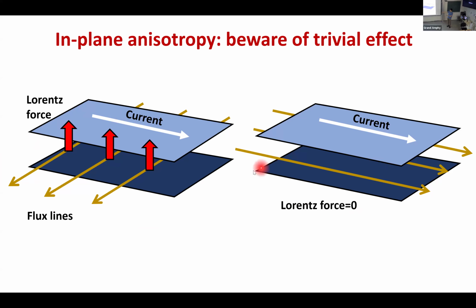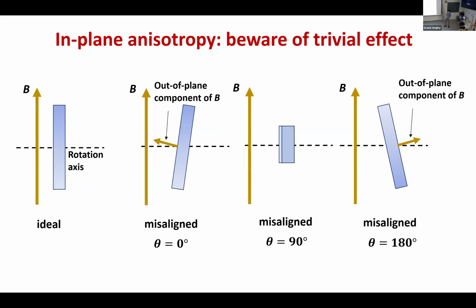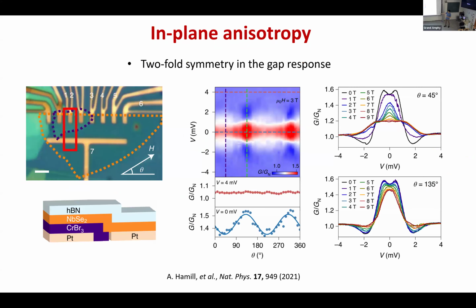So again you have something twofold, because you rotate perfectly in the plane with a full circle, but you get this effect 2 times. The Lorentz force reaches a maximum 2 times. So this can also induce a fake twofold symmetry. For the monolayer case, I would say it's really hard to imagine that the flux line can have such a strong effect. But for thicker films or thicker flakes, for example, the first one, here they have several layers. This is a tri-layer.